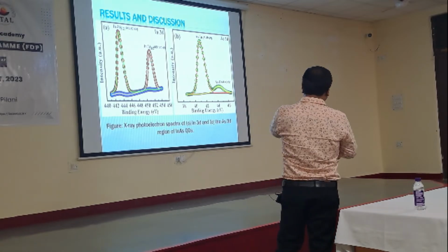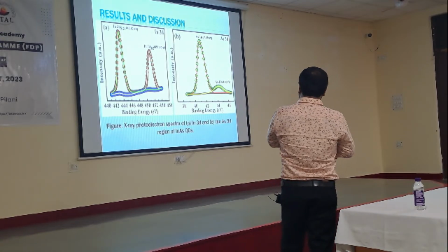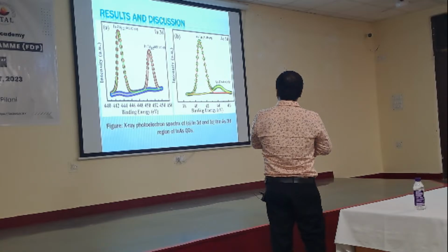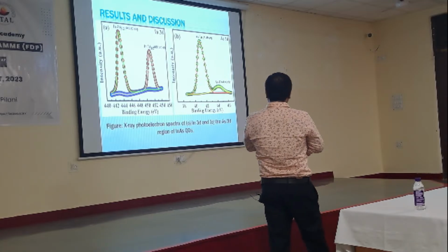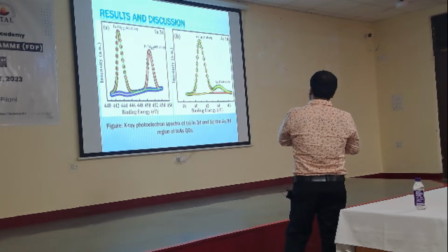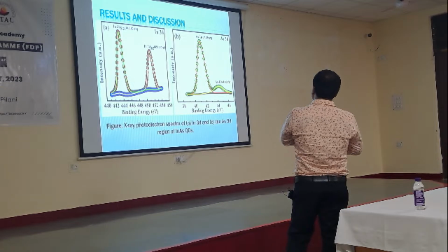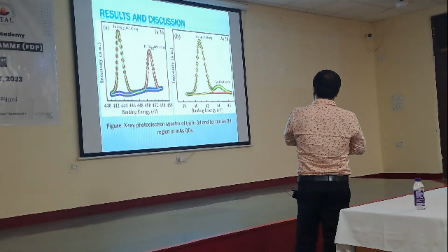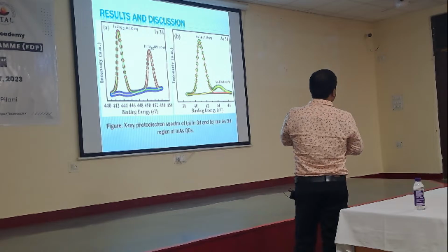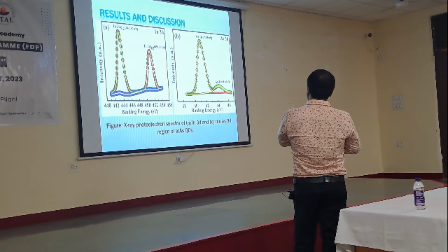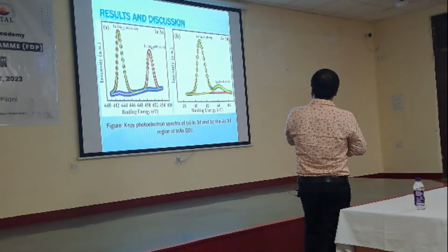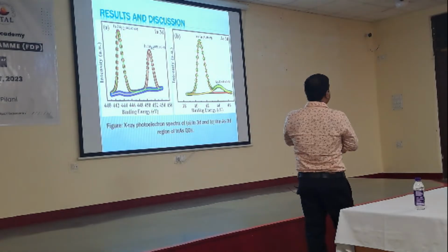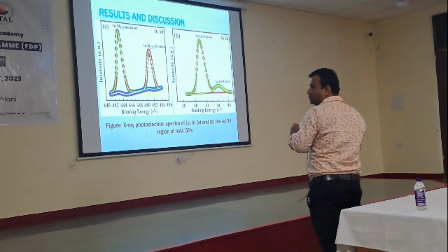Again, for that material we have used this one for arsenic. You see, this peak is responsible for arsenic and indium, and you see the intensity of this oxidized state peak is very low. So rather than formation of oxide, this material is formed. This again ensures the chemical composition of indium arsenide, nothing else. Next.